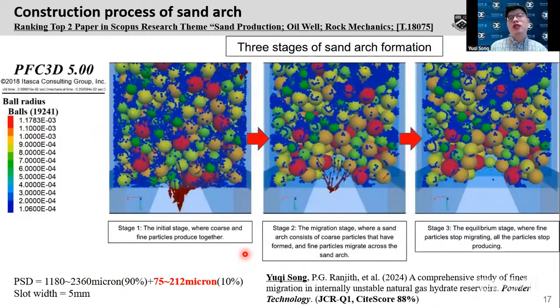In previous studies, I investigated uniform reservoirs and uniform strata, but in real cases, some strata might be well-graded or gap-graded. So here I investigate the construction process of the sand arch in a gap-graded reservoir. We can see that there are three stages of sand arch formation. At the beginning of the simulation, the coarse and fine particles are produced together. We can see the coarse particles, and the blue particles are the fine particles.